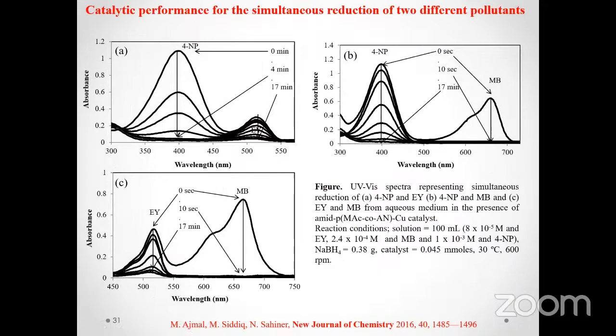In this work, we have also demonstrated the simultaneous reduction of a nitro compound and a dye, a nitro compound with a negatively charged dye, a nitro compound with a positively charged dye, and then positively and negatively charged dyes simultaneously, and then three different pollutants. One is the positively charged dye, second is the negatively charged dye, and the third one was the nitro compound simultaneously. And it was observed that this catalyst worked very well in all these cases as shown in this figure.